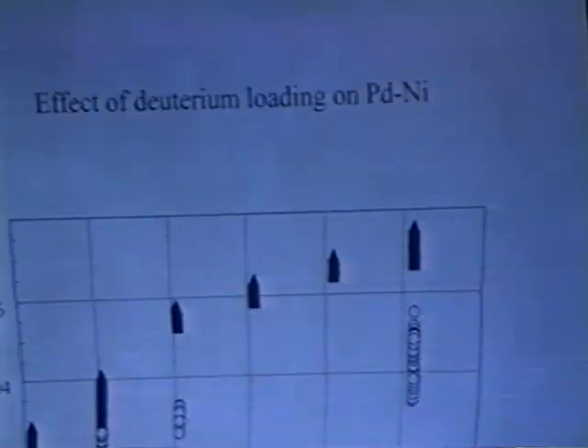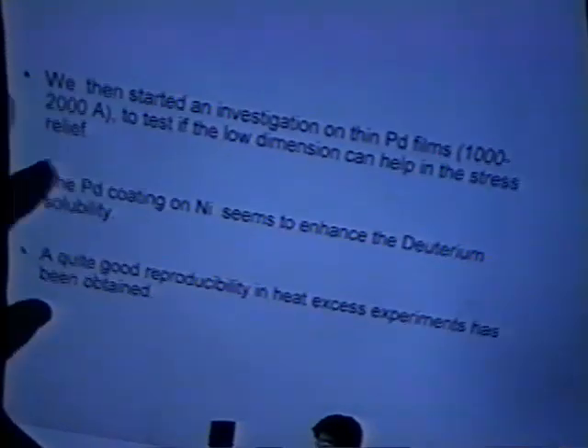This is the effect of deuterium loading. What we found is that the loading is higher in the case of Pd film on nickel with respect to nickel bulk. This is just a preliminary result, but we saw that this improved quite a lot the reproducibility of ICCF experiments.